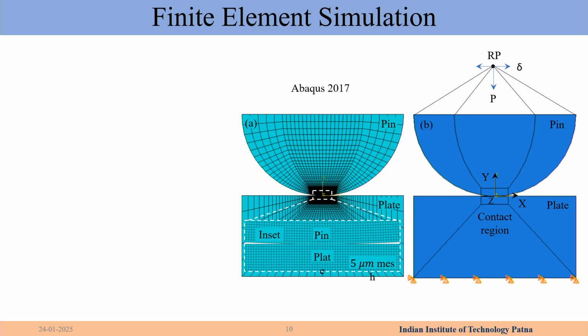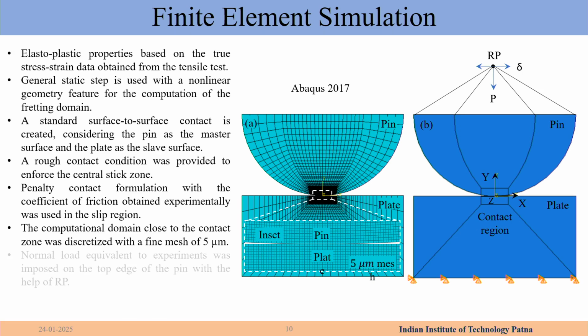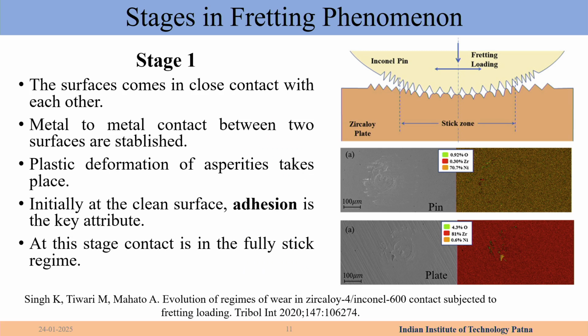There is a finite element simulation also, which Krishnamurthy has done in this. Again Abaqus, and some amount of crack modelling and all this was done. So again you can see there's very fine meshing which has been done at the contact. So what we find is that there are 3 stages to fretting from the experimental.